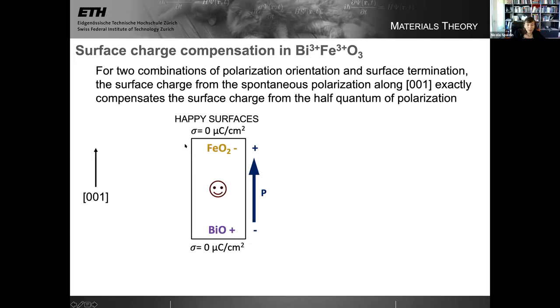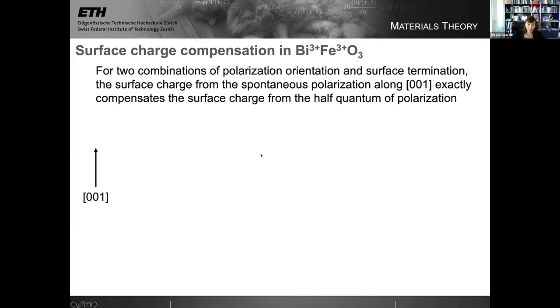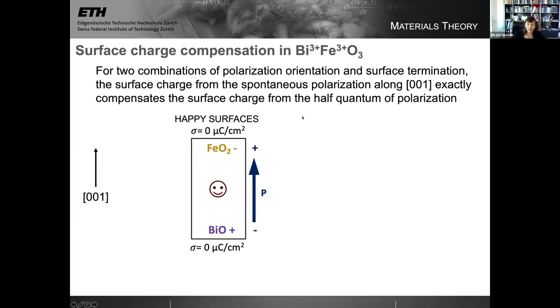So if, for example, I keep the same orientation of the bismuth ferrite, I have the FeO2 minus surface at the top and the BiO plus surface at the bottom, and I polarize it in the up direction, if I just leave the film sitting there, it will do this spontaneously, then the surface charge from the polarization exactly cancels the surface charge from the layer, and I get a net surface charge of zero. And so this is where we find happiness in our electronic structure calculations. This is a really happy, electrostatically completely content surface, right? There is no net surface charge.